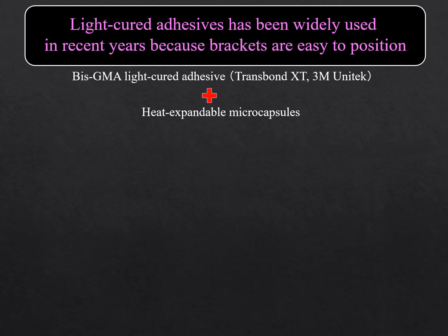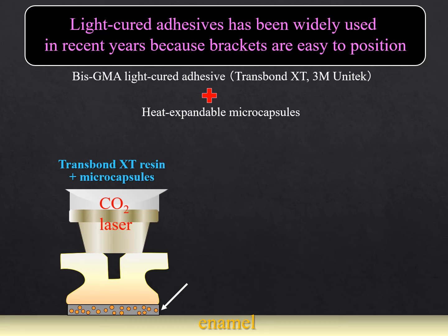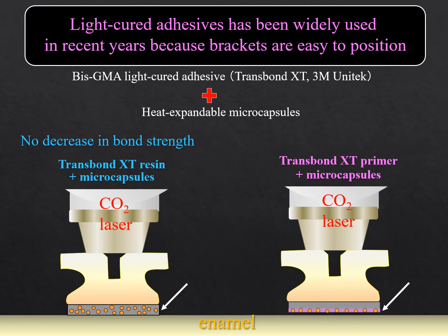Light-cured adhesive has been widely used in recent years because brackets are easy to position and many brackets can be bonded at once. Therefore, a similar study was conducted using this Bis-GMA light-cured adhesive. The product name is Transbond XT. At first, a preliminary experiment was conducted by mixing microcapsules in the resin paste of Transbond XT, as shown on the left. But there was no decrease in bond strength by laser irradiation. Therefore, the next experiment was conducted by mixing microcapsules in the resin primer instead of the paste, as shown on the right. The bond strength of the ceramic bracket was significantly decreased by the laser irradiation.